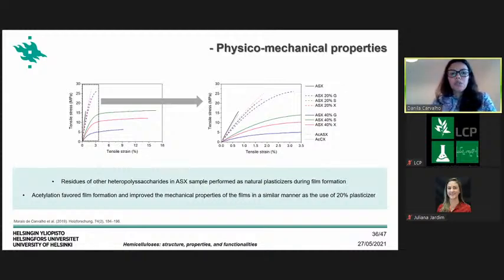So we could identify the beneficial aspect of using xylan containing some other heteropolysaccharide in the formation of the film, because they act as natural plasticizer. And also we could observe that the acetylation improves the mechanical properties in a similar manner as the use of 20% of plasticizer for our xylan.